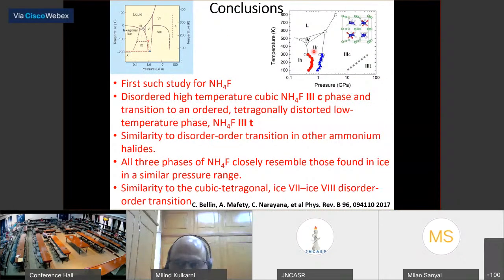You can actually summarize, and this is my last slide, to tell you what is happening in ammonium fluoride. So here is the temperature study which we are doing at higher pressure, at low temperature. It goes from hexagonal to a rhombohedral, then to a disordered cubic structure, which is similar to the ice VII structure. ice VII structure is this disorder. Now what is happening is, as you lower the temperature, you bring ordering into the system, and this ordering is leading to a tetragonal phase.